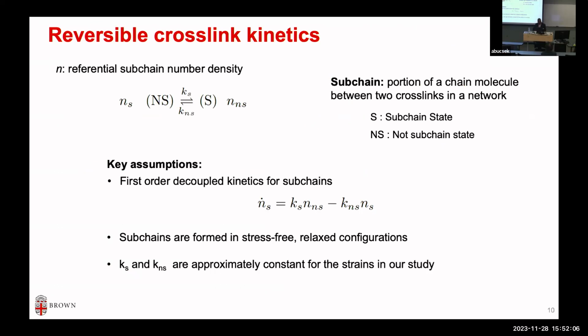So having seen those experiments, even the one-dimensional experiments of the physical behavior, now we want to develop a model. We know that the polymer's macroscopic behavior is coming from the cross-linking, the network level small scale behavior, which is cross-link dominated, right? So we said, let's take the first order approximation. The kinetics of these crosslinks being formed and broken is first order.